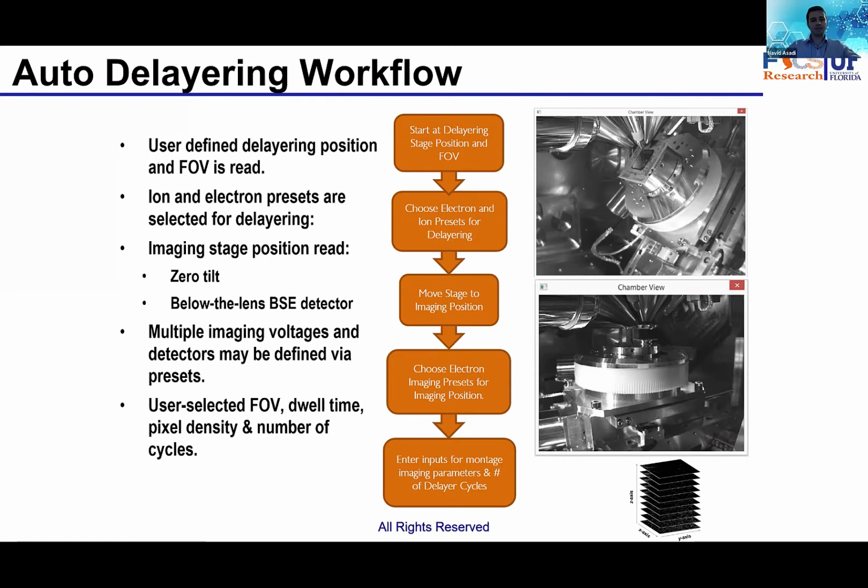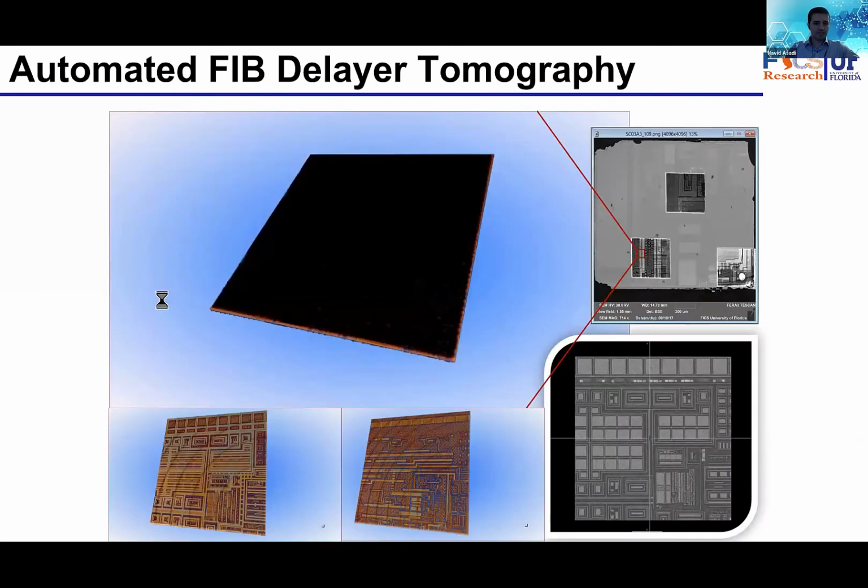which will include about 40 or 50 different slices. Every slice where material is removed may include a portion of a layer; every layer probably involves 2 or 3 slices. So we have to remove the material slowly to make sure we capture those nanometer or sometimes even smaller than nanometer features. Once we have that, the stack of images can be created.